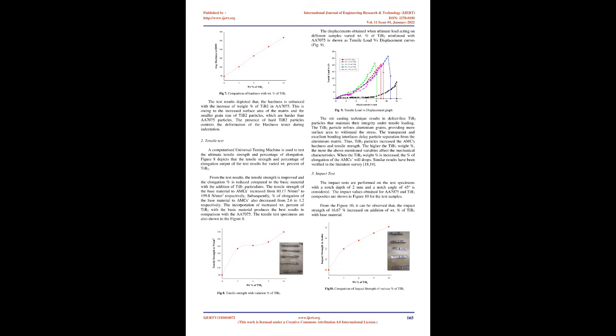When particulates are introduced externally, a number of variables, including pore weight, pore agitation, and density difference between matrix alloy and TiB2 particles, lead to cluster formation. Further, when particles are introduced externally, local melt temperature lowers. The connection between particles is weak in clusters, resulting in low mechanical characteristics. However, the reaction shows excellent bonding of particles in clusters produced by the stir casting approach.